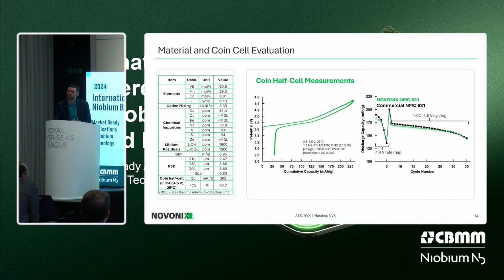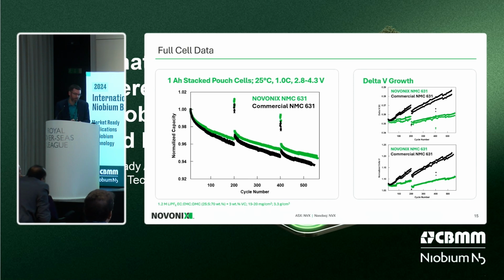So we were quite pleased with these results, and what we really needed to do, though, was test what this material could do in a full cell to really understand how well our cathode powder could be in real applications. So we turned to our team to construct 1 amp hour stacked pouch cells, and these are the data. The left-hand side of the slide shows normalized discharge capacity versus cycle of our material highlighted in green against that commercial NMC631 powder. And what we can see is our cells are very competitive, I would say even an improvement over commercial NMC cathode materials, at least at 25 degrees Celsius and 1C rate.